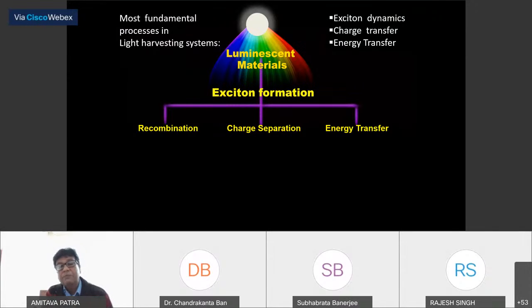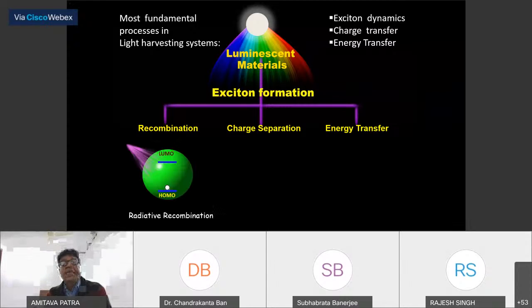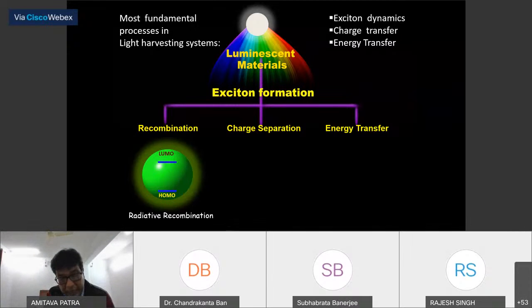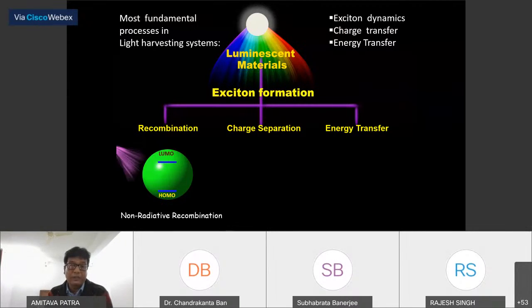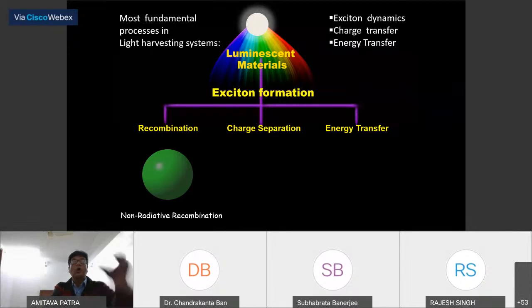So what are the fundamental processes for a light harvesting system? Three important processes you have to understand. Photophysical process. One is exciton dynamics. That means the electron goes from the valence to the conduction band. They will recombine. This is a radiative recombination process. Otherwise, there is a non-radiative process. The electron goes and they will interact non-radiatively. So the whole relaxation process you have to understand by time resolved spectroscopy. Otherwise, you cannot design your nanomaterial if you don't know the relaxation process.